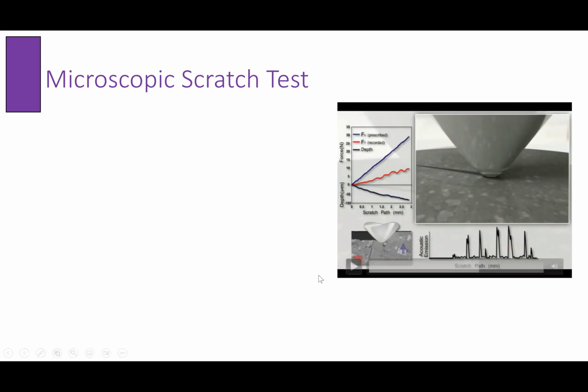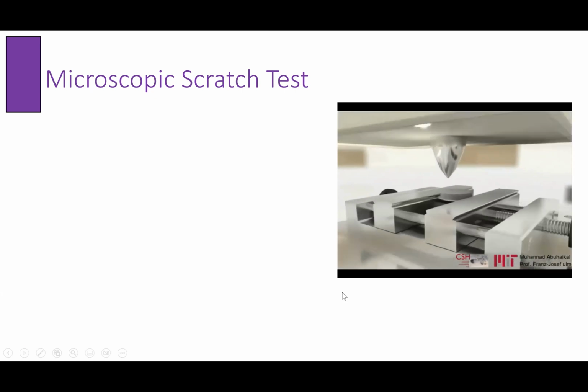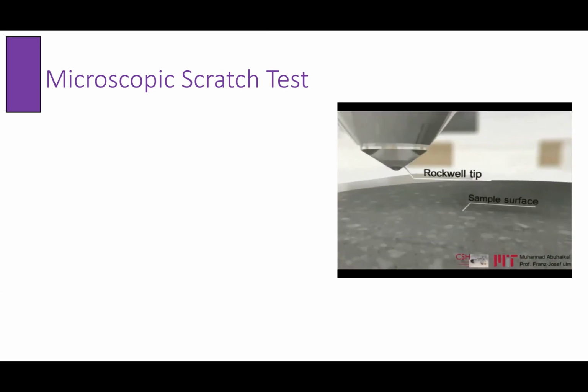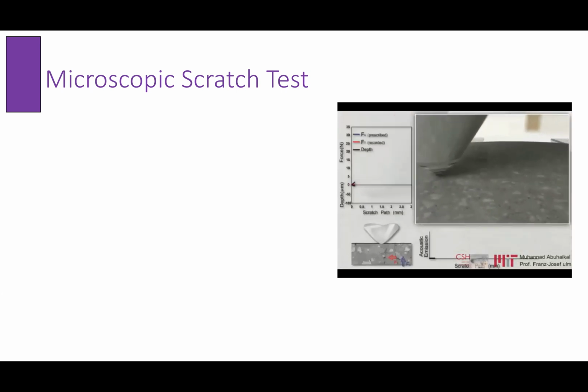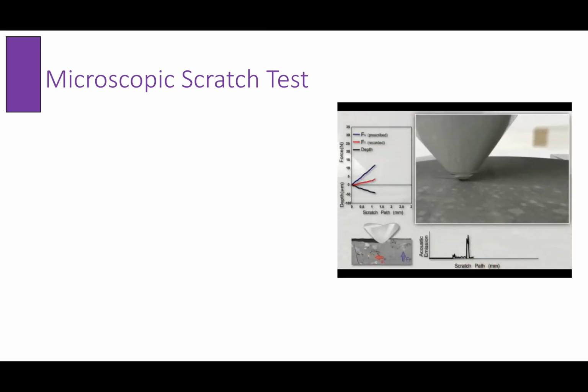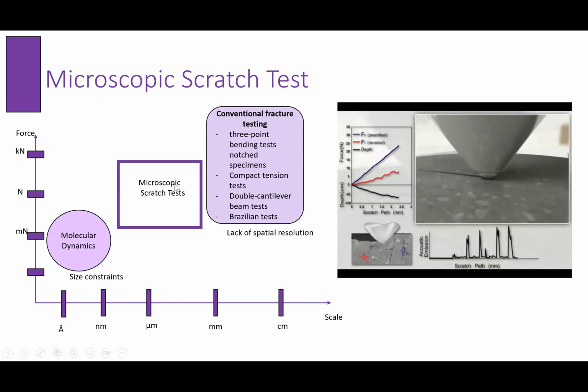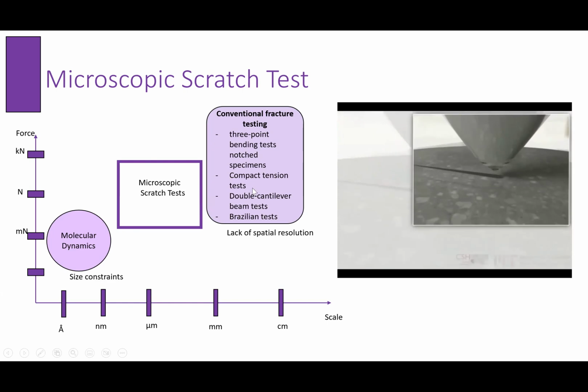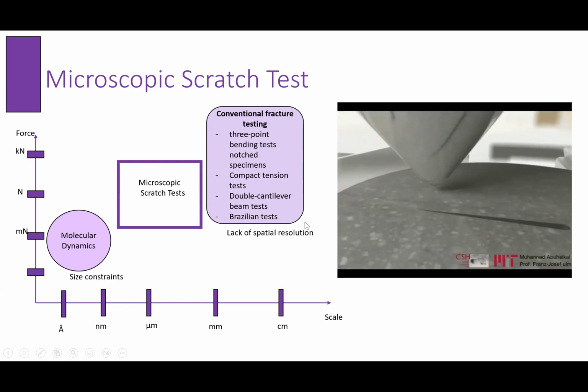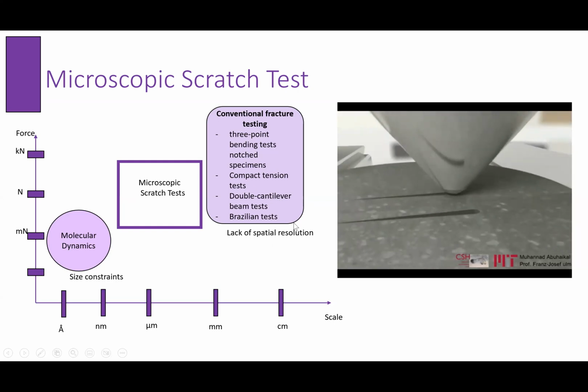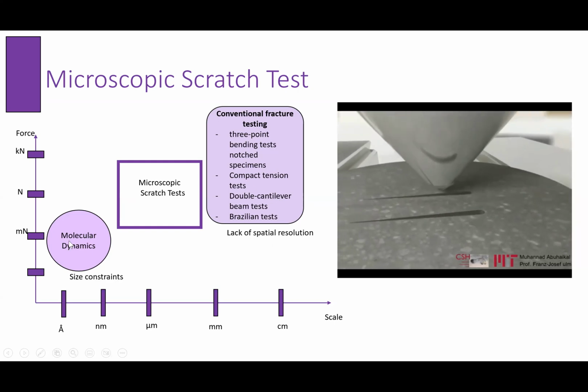One of the advantages of using that method in this case is that it requires a small amount of sample. The scratch length is a couple of millimeters, and the depth we're going to go is tens of microns to hundreds of microns. And yet we are able to have meaningful information regarding the mechanical properties, in this case, the fracture behavior. What is really good is that this scratch test enables us to bridge the gap between conventional fracture testing methods at the millimeter length scale, and molecular dynamics at the nanometer length scale, where it's challenging to find matching experiments at a lab scale. Good.